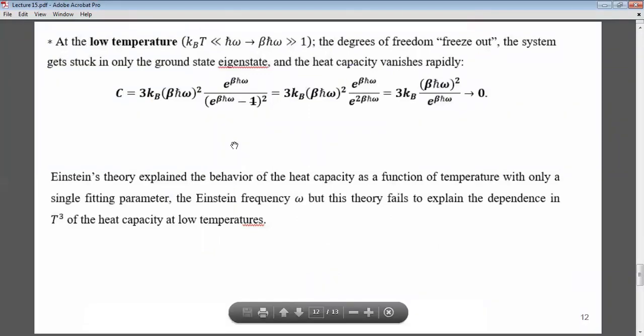Now, Einstein's theory explained the behavior of the heat capacity as a function of temperature with only a single fitting parameter, the Einstein frequency omega. But this theory fails to explain the T cube dependence of the heat capacity at low temperatures. He did all his measurements by taking omega as fixed, but in reality, there is also dependence on the temperature, and it's a T cube dependence. This is what is not found in his calculations. There is no T cube dependence. And this is what Debye will show in future lectures.